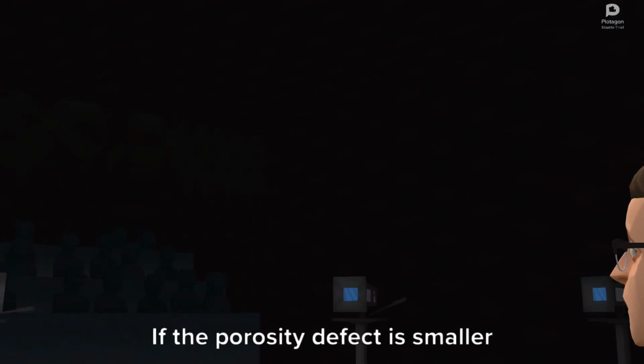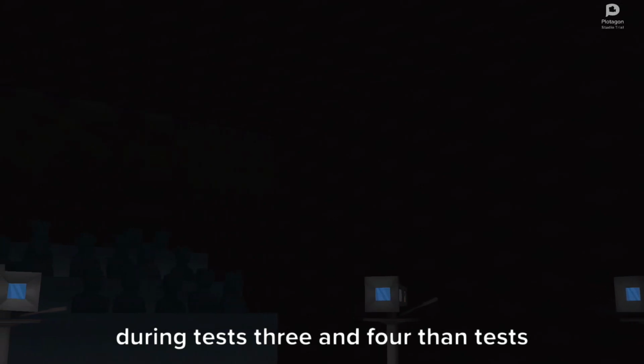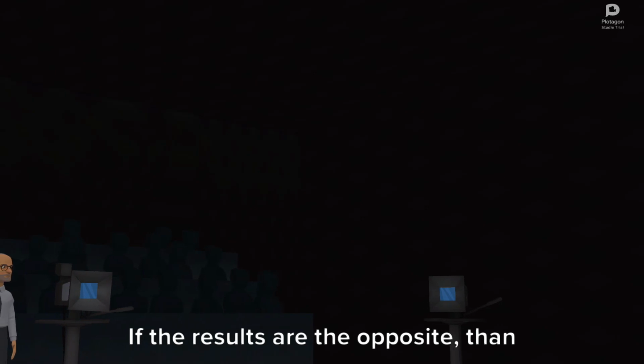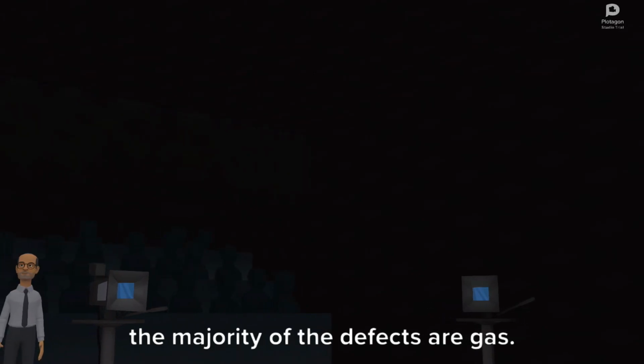If the porosity defect is smaller during tests 3 and 4 than tests 1 and 2, the majority of the defects are shrinkage. If the results are the opposite, then the majority of the defects are gas.